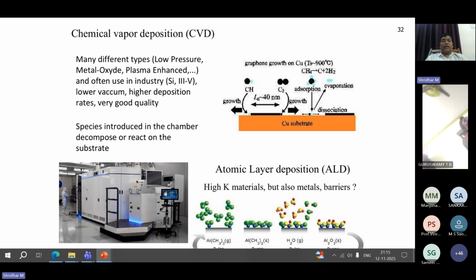Okay. And species introduced in the chamber decompose and react on the substrate. Assume that I want to deposit graphene growth on copper; see here, this is graphene deposited on copper. What they do is give high energy and plasma will be created, and the carbon active material will evaporate and deposit on the substrate, whatever substrate. Here they considered copper. We can consider PET sheet also, silicon chip also, germanium substrates also. It is based on the requirement.